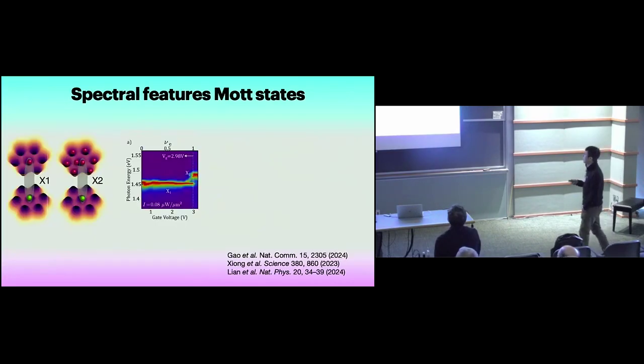Okay, so in the experiments, what we did is to exactly probe this kind of structures, and I want to mention that this similar phenomenon was observed by Chenhao Jin's group here at UC Santa Barbara, and also Sufei Shi's group. Here I'm looking at a low pumping power regime. So relatively speaking, I'm putting fewer excitons compared with electrons. When I go to this half filling state, suddenly there is a jump in the exciton energy corresponding to the transition between this empty site exciton X1 and this doubly occupied exciton X2.